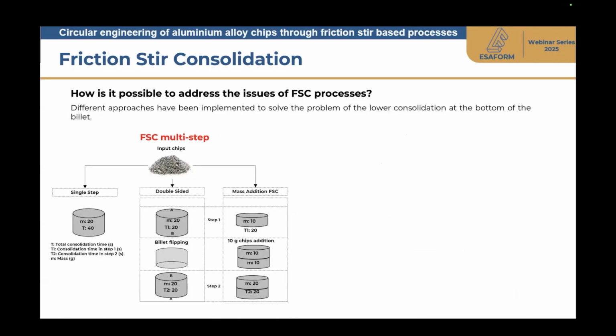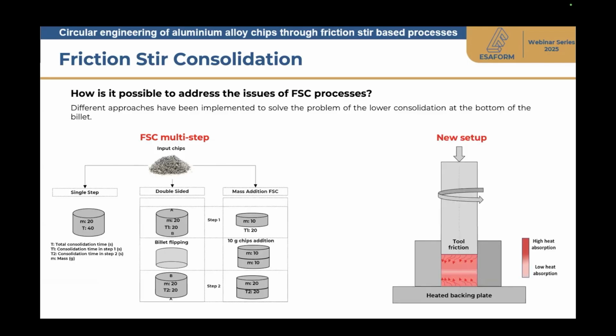Well, the idea, of course, in the process is to get the best homogenization of the material in terms of mechanical characteristics as it is consolidated. In order to get this result, we investigated two different approaches. The first one is so-called friction stir consolidation multi-step, namely the possibility to interrupt the process, to flip the billet, and to complete the process with the flipped billet in the second part of the process, or to have a mass addition approach, namely to use the half of the material to carry out a first consolidation, to add the second half of material, and then to carry out the second stage of the consolidation.